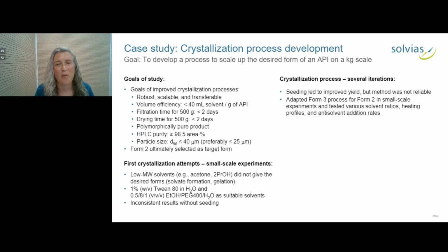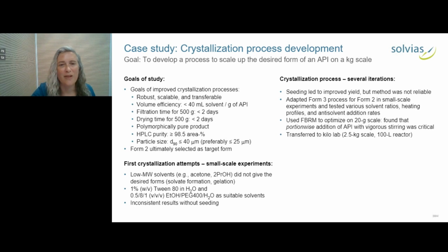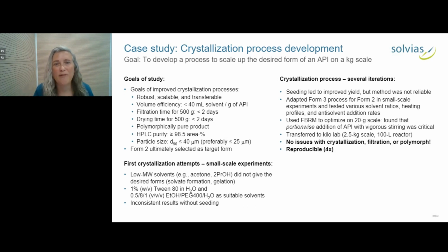So these are milliliter scale experiments, and varied solvent ratios and heating profiles and anti-solvent addition rates, stirring rates, et cetera. And then we used the focus beam reflectance measurement on a 20-gram scale and found that it was very important to add this API portion-wise with very vigorous stirring. And we were able to come up with a process that we could transfer to the kilo lab on a 2.5 kilogram scale in a 100-liter reactor. And it worked very well in the sense the crystallization went smoothly. There was no problem to filter it. We got the correct polymorph, and it was reproducible. It was run 4 times on this kilo scale without a problem.